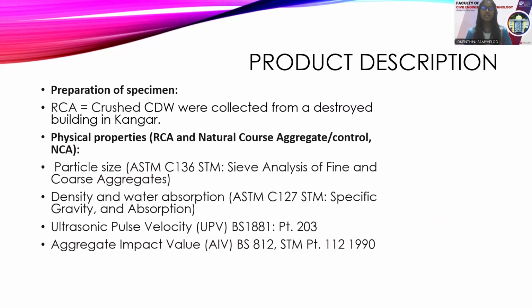The first, particle size analysis, sieve analysis for the fine and coarse aggregates. Second, density and water absorption, specific gravity and absorption of water. Third, ultrasonic pulse velocity, which is called the UPV test. And fourth, aggregate impact value, the AIV test.